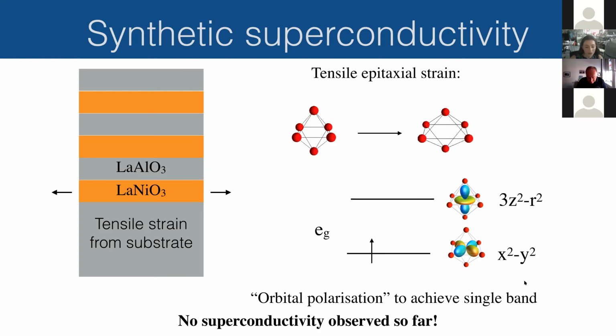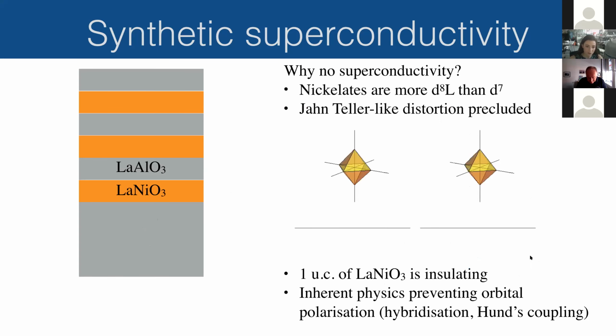Now, what I have to tell you is that no superconductivity was ever observed for these types of structures. And the reasons are probably numerous. I'm going to explain 4 possible reasons. The first one, I mentioned at the start, that nickelates are actually not so much D7. This was not really appreciated when people started to look at them for superconducting properties in the 90s, but they are more like D8L with this ligand hole. So already you're starting from an electronic structure that is not so good.